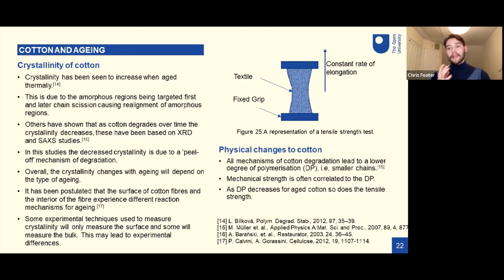An interesting thing that I read is a study that postulated that the surface of the cotton fibres, so the cellulose near the surface and the cellulose in the interior of the fibre, so the bulk of the fibre, will actually experience slightly different reaction mechanisms for the degradation. And looking back at these studies, some of the experimental techniques used to measure the crystallinity were only actually measuring the surface, and some were measuring the bulk as a whole. And so this could possibly, in my opinion, lead to some experimental differences. And also some could argue that some methods to determine crystallinity are more accurate than others.